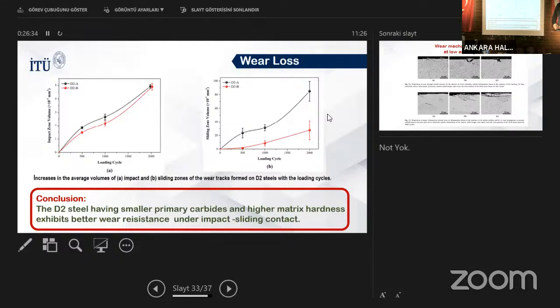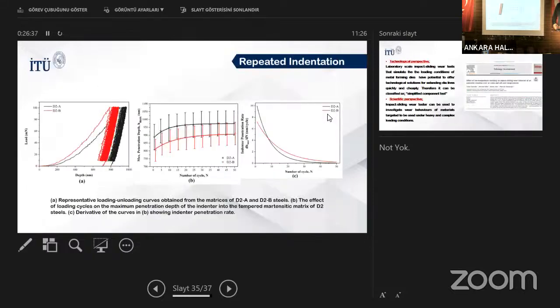What we finally have done? I'm skipping all those ones. Indentation. We have run an indentation test under this load, 100 millinewtons, and at the same point, 500 loading cycles have been employed, and we have determined the depth of the indented penetration. So this is the depth of indented penetration, and this is the number of cycles. With increasing number of cycles, indented penetration is larger. Okay, so this is the evidence of cyclic softening.